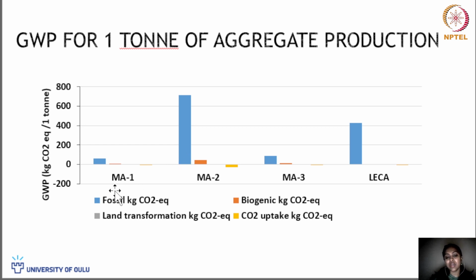However, when you think about the 70% utilization of ready-mix concrete fines and also geopolymer concrete fines, the emission for the methods that we used here as production technology is way below what we could expect from the commercial aggregates.